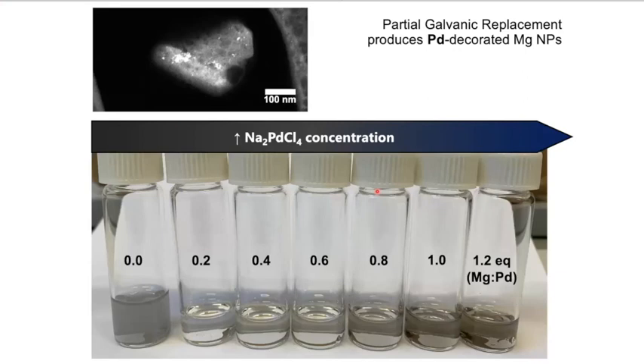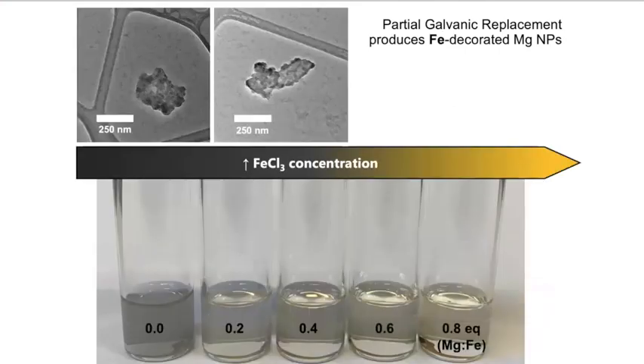And there's a huge broadening because of this aggregation. We can do this with more catalytically relevant metals. So this is an example of palladium that we've been able to decorate, and we do retain the plasmonic properties of the magnesium and add the catalytic surface of palladium. And I just hired a new postdoc from Oxford, and he's there to do a lot of catalysis, both liquid phase and gas phase catalysis and photocatalysis on these. So this is really an exciting development.